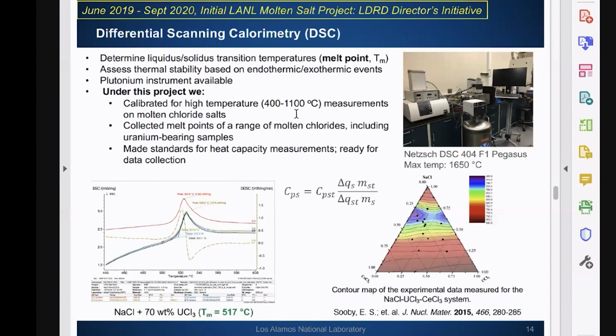We've collected melt points for a range of molten chlorides, including uranium-bearing samples. We've made standards for our heat capacity measurements, and now we're ready for data collection, and that's coming up in the next couple of months. What I want to point out here is that we do have this instrument available in the Plutonium facility, and so we're ready to make those measurements once we get that material.